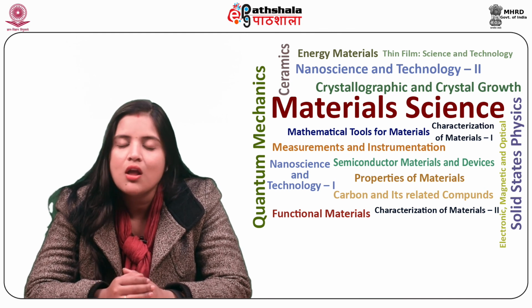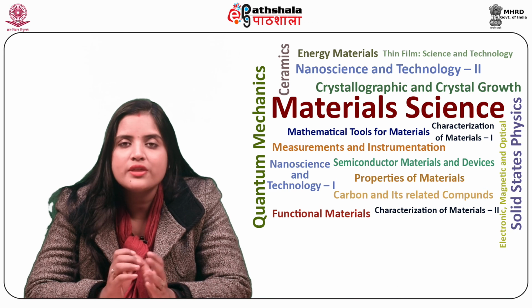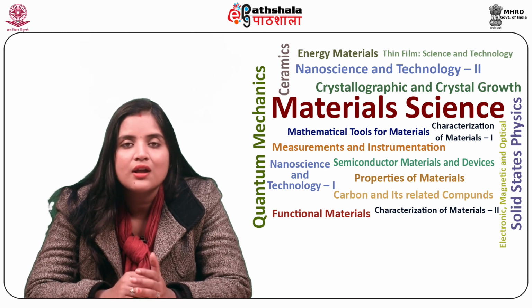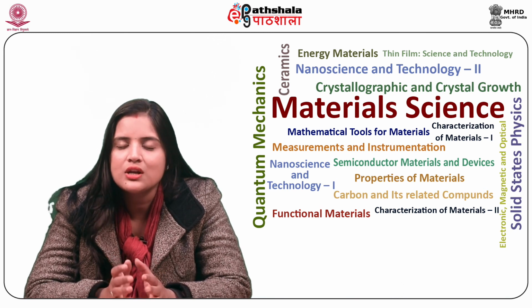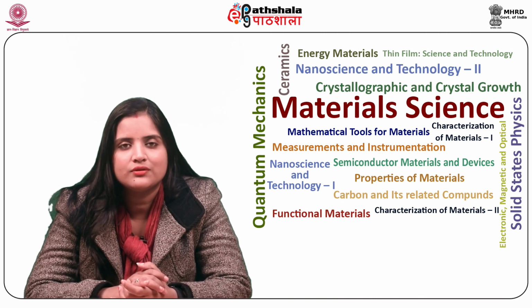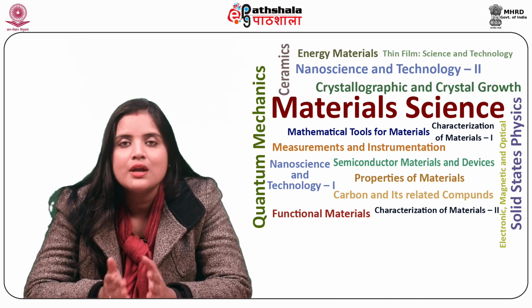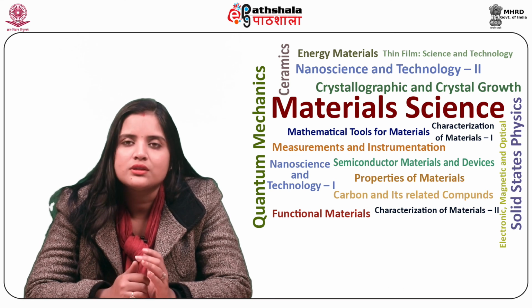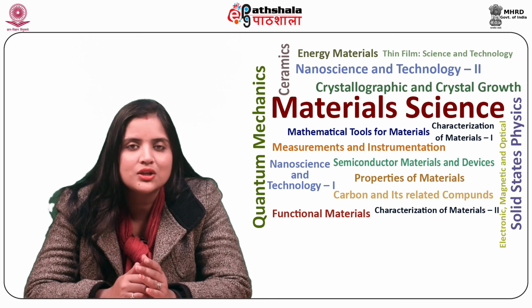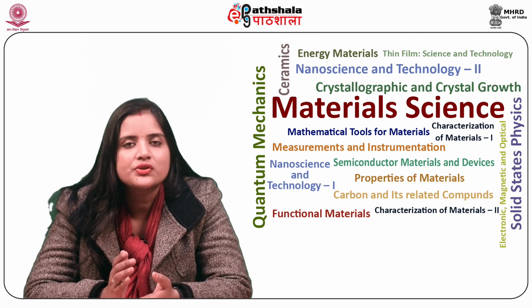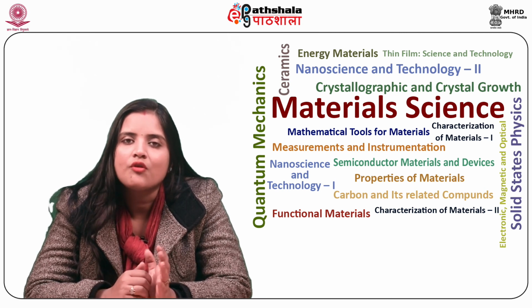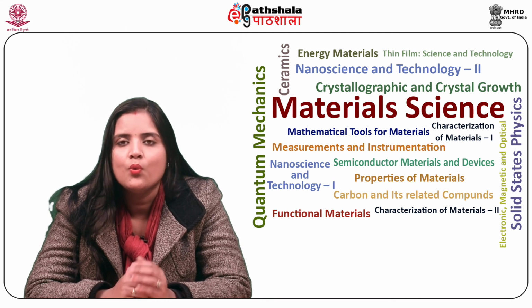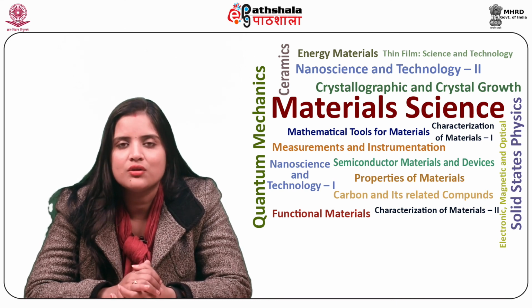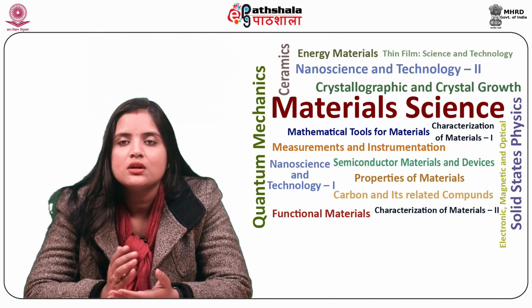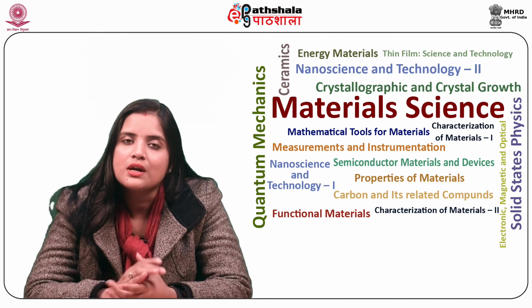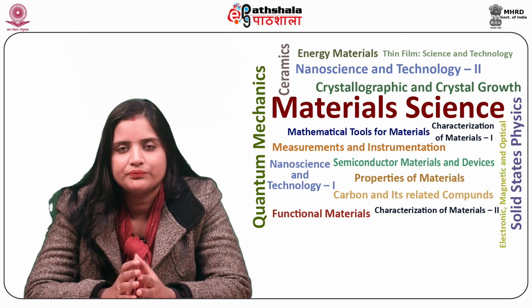Deposition temperature influences all these processes barring the aerosol formation and transportation. Therefore, temperature of substrate is the most important parameter which determines the structure and properties of deposited films. With rising temperature, film morphology transforms from cracked into porous.